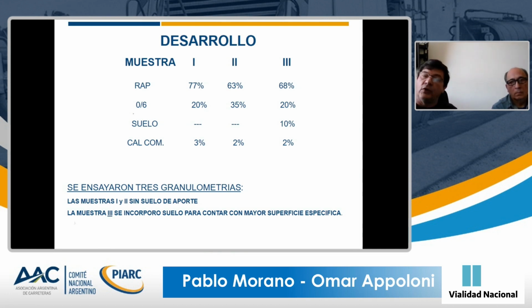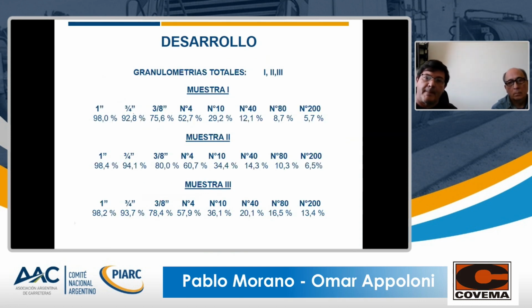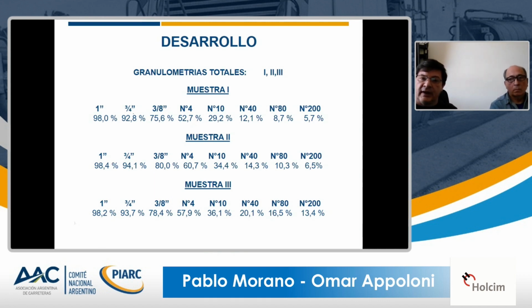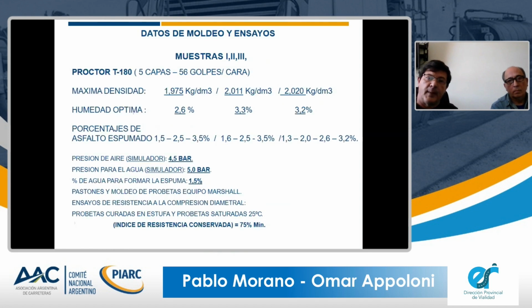So what you see here is that both sample 1 and 2 did not have added soil, and in sample number 3 we had added soil. These are the curves that we can see from the 3 types of samples, where we can see that sample number 3 is the one with the most added fines, so that the mix of foam, asphalt, and fines was the perfect one to get the cohesion that we were looking for and the binding that we were looking for.